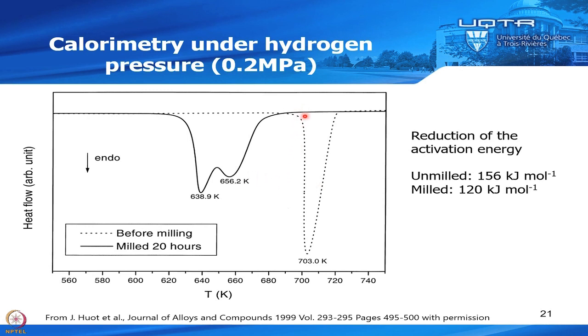Okay, and you notice that here I have only one peak and here I have two peaks. But you remember that in the ball milled material, we had two phases. We had the gamma phase and the beta phase. So that's why I have two peaks here now. One of them is the desorption of the gamma phase, and the other one is the desorption of the beta phase. Here I just have the beta phase, but you see a reduction of that temperature peak. So it means that I have a reduction of the activation energy. So we could measure that, and for the unmilled one, the activation energy was 156 kilojoule per mole, while for the milled one, it was 120. So that's one of the reasons why the kinetics is faster, because the activation energy is lower.